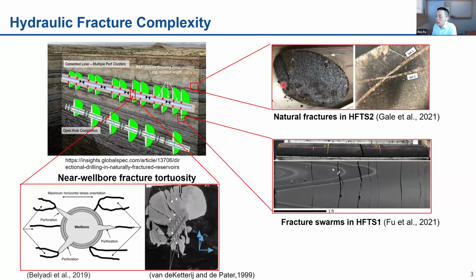So it can be natural fractures in the subsurface, and also instead of initiating one single fracture from each of the clusters, which has been widely assumed nowadays in the industry, some recent field tests also reveal that there are more complex fracture features, especially as shown in this plot. This is a 3-foot long core and we can see 8 of the fractures clustering within this single core. So it is growing in a swarming manner within a very short distance.